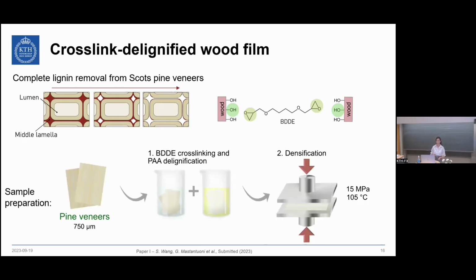So the materials were prepared in three steps. First we have the BDDE cross-linking. This was followed by peracetic acid delignification. The reason for this is that we wanted a slightly milder delignification method so that we could preserve as much as possible of the hemicellulosic content. Finally, this material is densified at high pressure and high temperature.